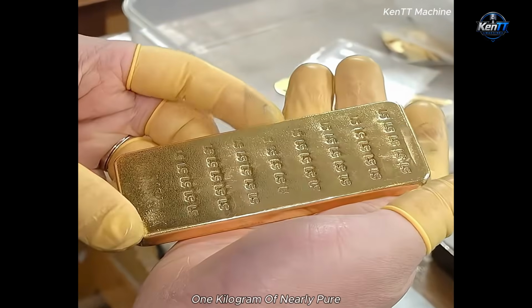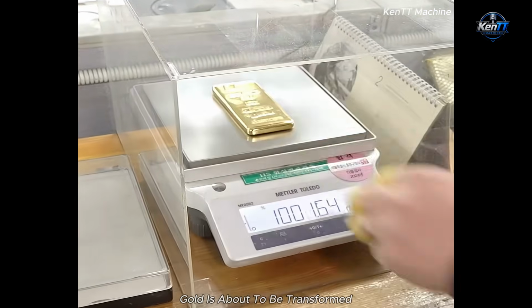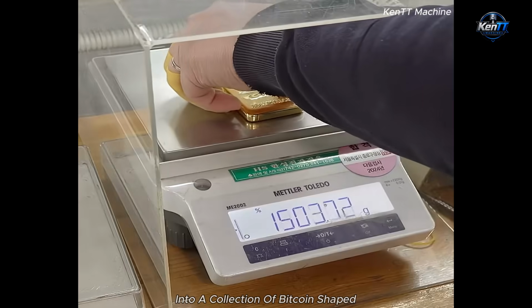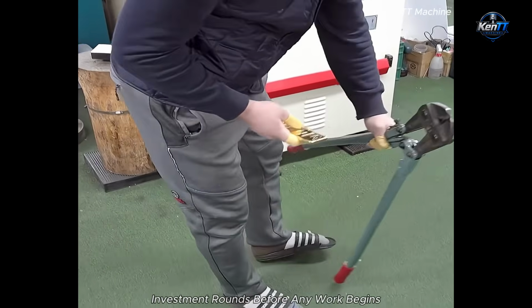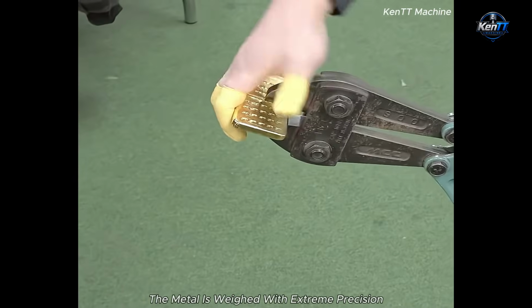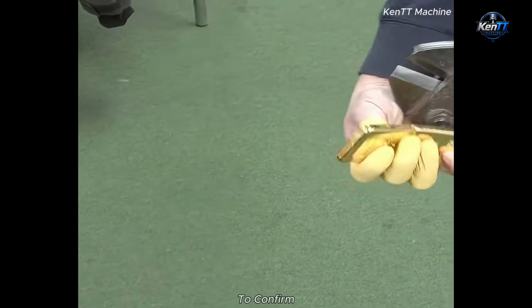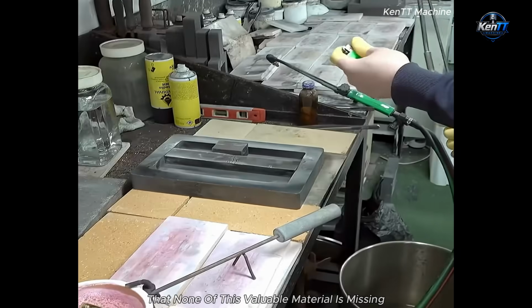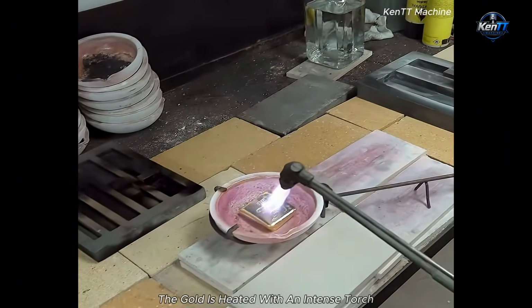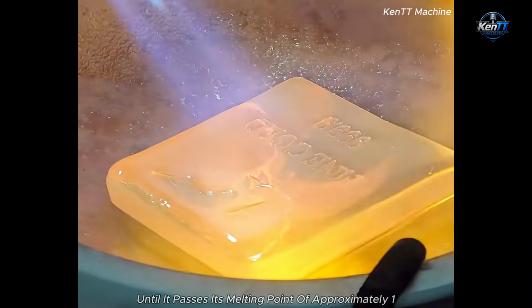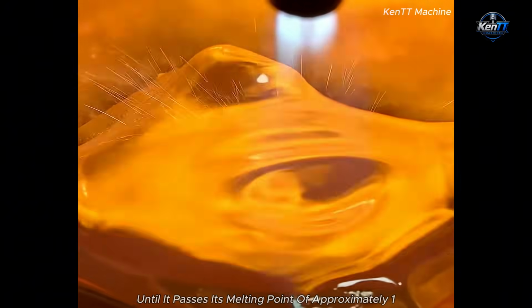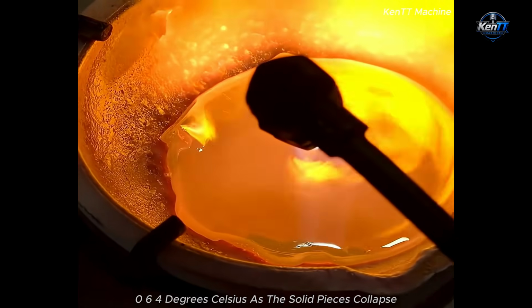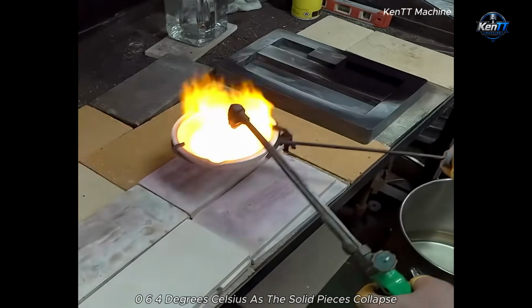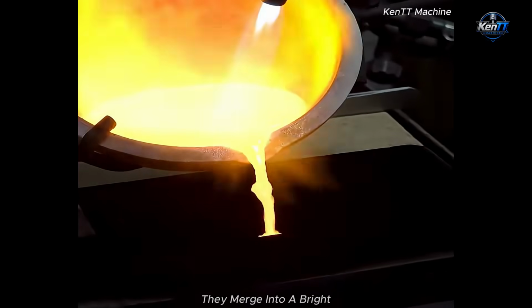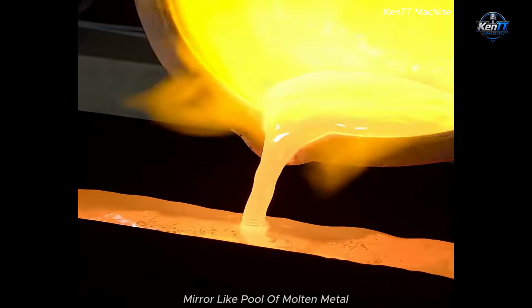One kilogram of nearly pure gold is about to be transformed into a collection of Bitcoin-shaped investment rounds. Before any work begins, the metal is weighed with extreme precision to confirm that none of this valuable material is missing. The gold is heated with an intense torch until it passes its melting point of approximately 1064 degrees Celsius. As the solid pieces collapse, they merge into a bright, mirror-like pool of molten metal.